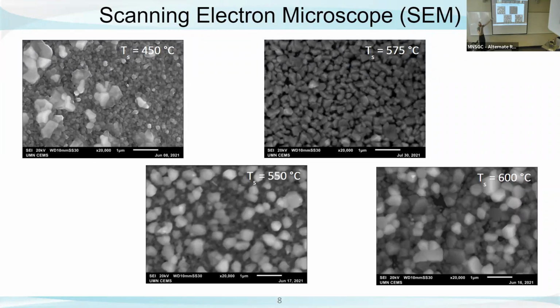And then as we hit 575, we see exactly what we want to see, with all of our grains being the same size. And then as we increase the temperature more, we want to just see what the effects were. We did get a good film, but we wanted to increase even more. And as you can see, those larger grains start to come back. And there's also a couple of holes that start to form within our samples. So we do have a nice look at our film, but we don't know if the film is actually made up of what we want it to be made up of.